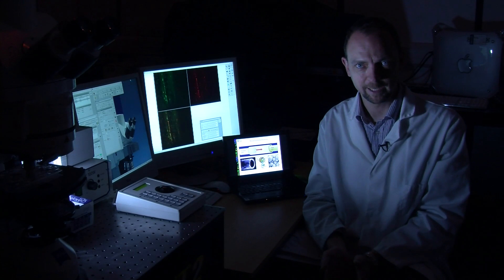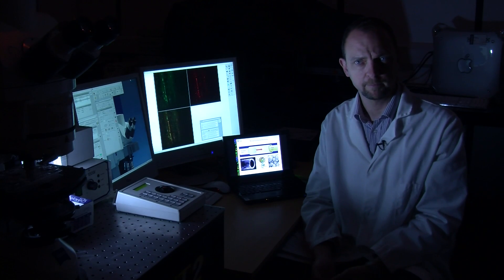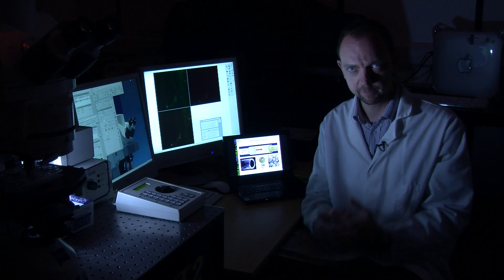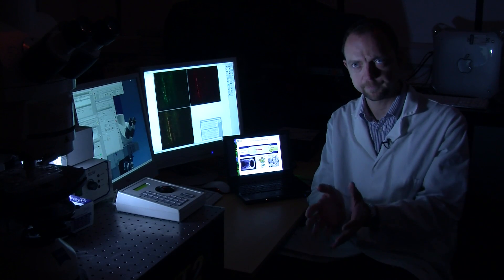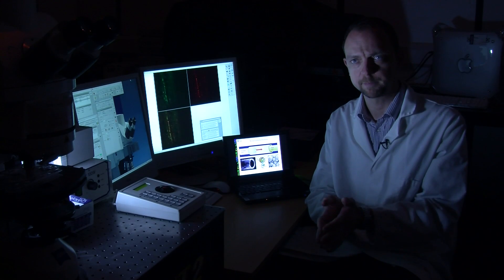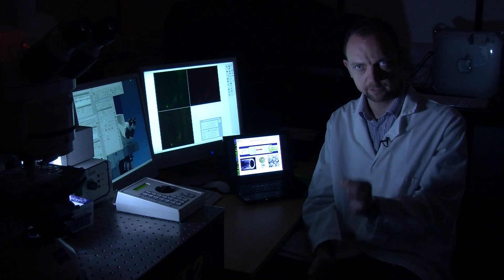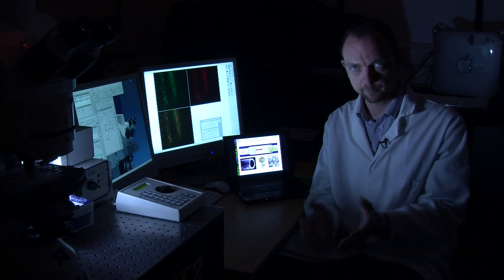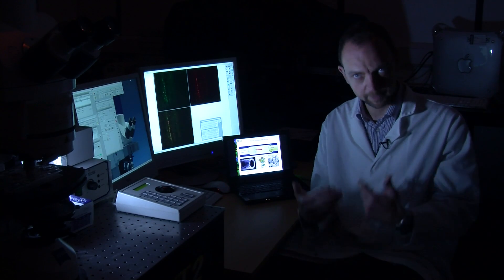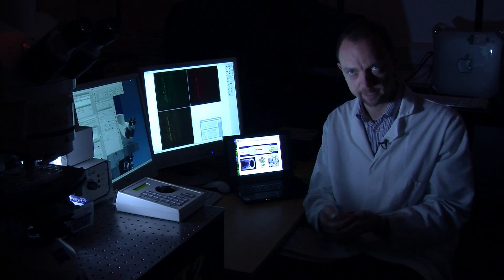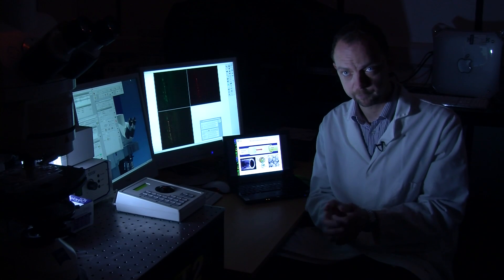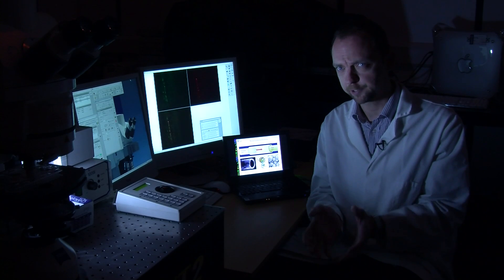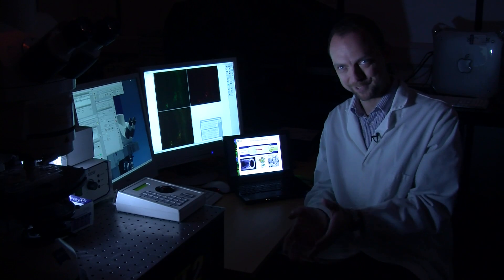What we have here are aligned fibers made from a synthetic polymer called polycaprolactone. We've made thousands and thousands of these as a scaffold. The size of those fibers is absolutely critical because the size of those fibers is the same size as the individual nerve cells that we are trying to regenerate. We've then put the nerve cells onto those fiber scaffolds and they have grown along that. The big question is, do those cells actually grow on the fibres, or to put the question the other way around, does that scaffold actually support the growth of those nerve cells?